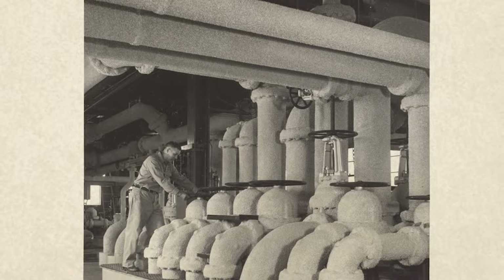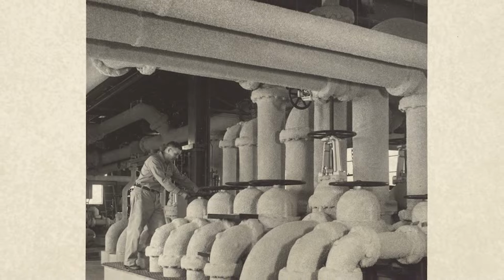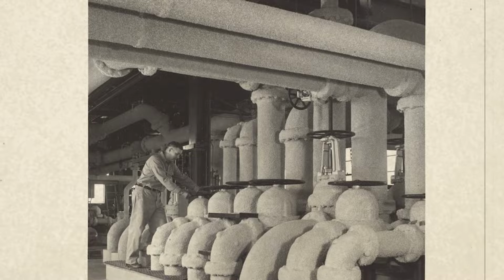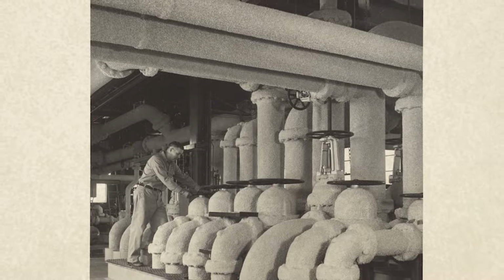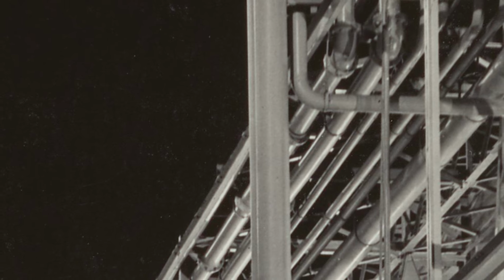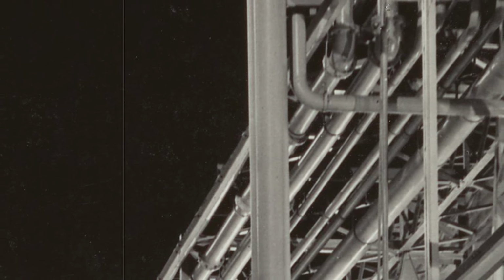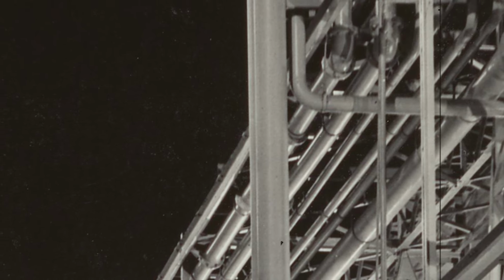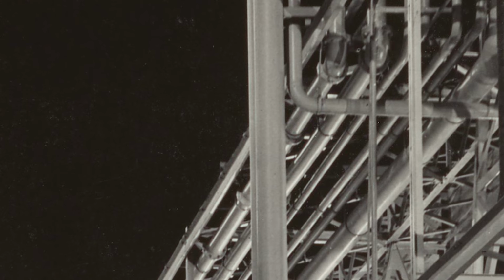From the flocculators, the magnesium-rich slurry flowed into Dorr thickeners that separated the precipitated hydroxide from the processed seawater. These circular settling tanks, each over 100 feet in diameter, used carefully controlled overflow rates to concentrate the magnesium while allowing the depleted seawater to return to the Gulf. The engineering precision required was extraordinary. Too fast a flow rate and valuable magnesium would be lost. Too slow, and the entire process would bottleneck, shutting down production.